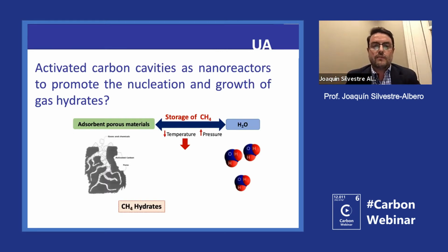So our main focus at this time was, okay, can we make these hydrate crystals artificially, and can we take advantage of the cavities in our carbon materials to promote the growing of these specific crystals? That was our open question, no? Because we knew that in the natural environment, the association of water with methane to make these hydrate crystals is a process that needs high pressure and low temperature.